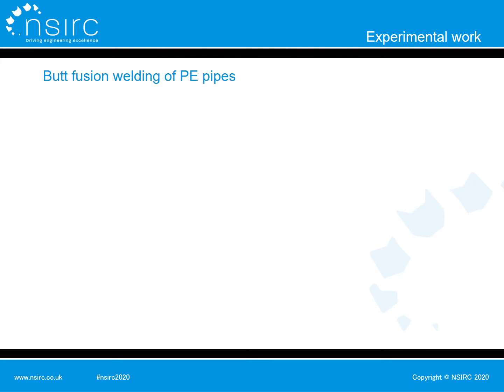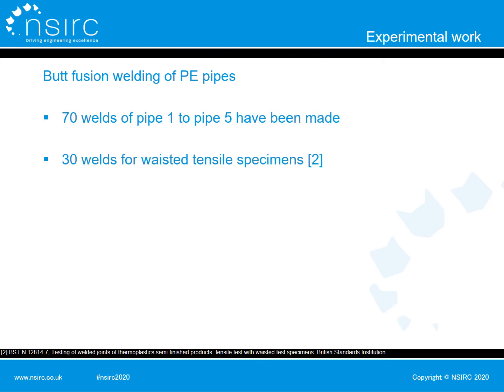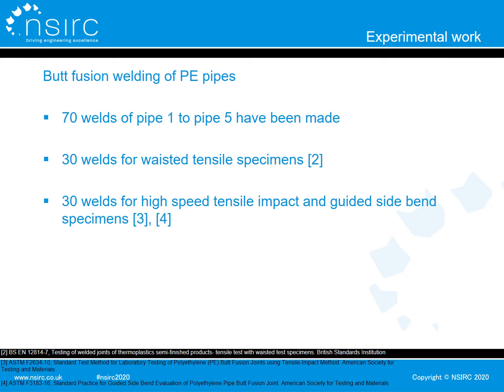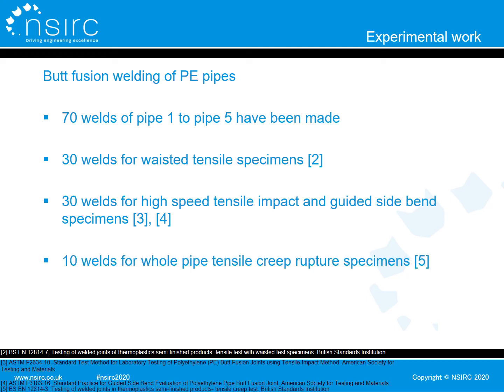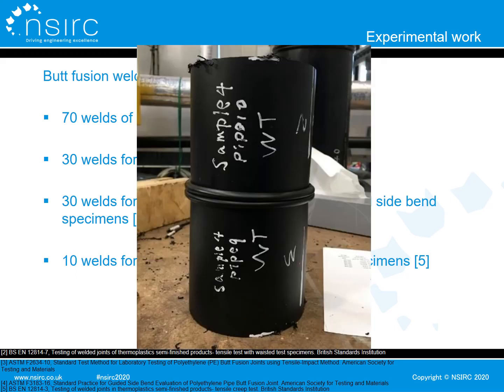So far, 70 welds of pipe 1 to pipe 5 have been made. 30 of them were made for waisted tensile specimens, 30 of them were made for high-speed tensile impact and guided side bend specimens, and 10 of them were made for whole pipe tensile creep rupture tests. Here is an example of a joint made for a waisted tensile test.